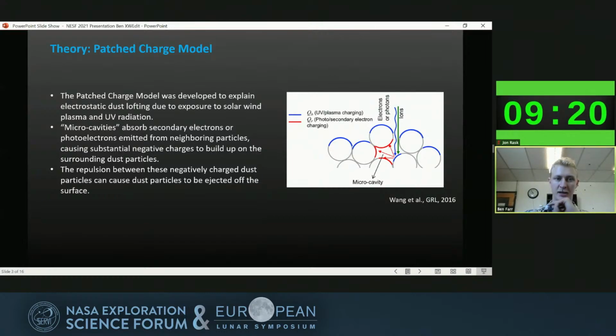So our experiment is based on a theory called the patch charge model. The patch charge model was developed to explain electrostatic dust lofting due to solar wind exposure and UV radiation. The theory postulates that if you have a dust layer, there are microcavities between all the dust particles. And when the dust is bombarded with UV radiation or solar wind, that generates secondary electrons or photoelectrons that are emitted from neighboring particles, and those build up inside those microcavities and eventually give you a really large negative force, which then forces the particles to jump away from each other. So that's what we're basing this dust mitigation method on.